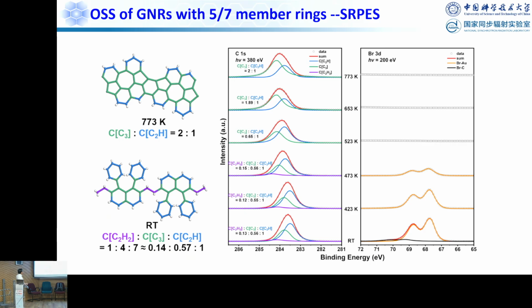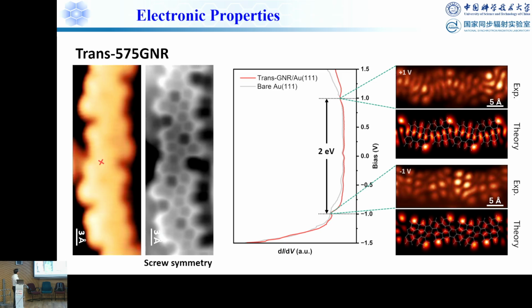structures on the surface. And this is proved by synchrotron radiation photoemission spectroscopy. Here the different colors show carbon atoms with different chemical environments. You can see at room temperature the Ullmann coupling already happens. You can see this green peak, which is only the carbon peak, and the blue one with the hydrogen, and you can see that with temperature this goes up. This is the reaction happening. Okay, and here you see we formed this trans 575 GNR, graphene nanoribbons, with atomic resolved